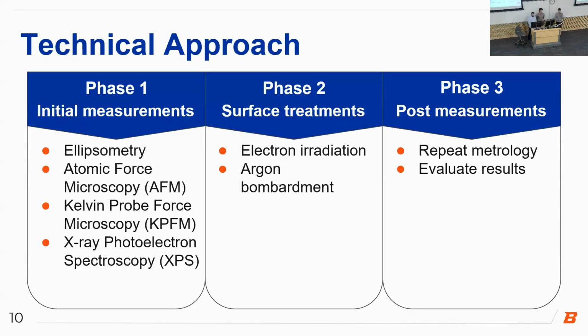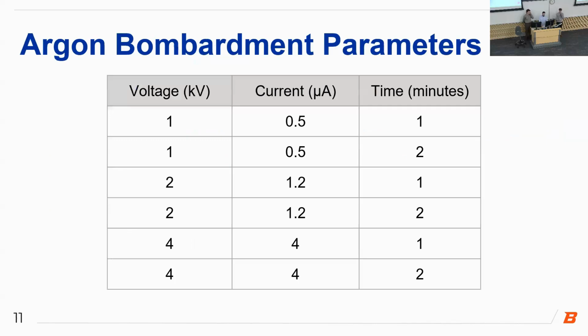As David mentioned, we had three phases of our project. Our phase one was doing ellipsometry, AFM, KPFM, and XPS to determine our initial measurements. And then we entered phase two, which were our surface treatments of electron irradiation and argon bombardment. And then finally, we did our metrology again to get our final results, and then we evaluated them.